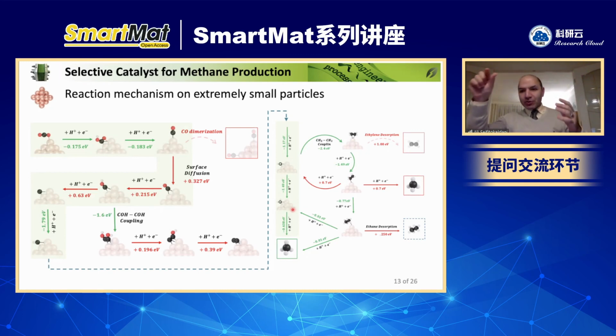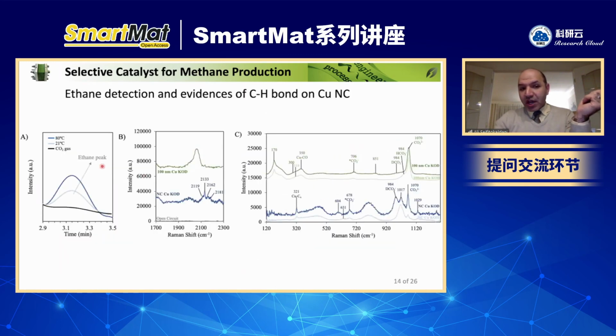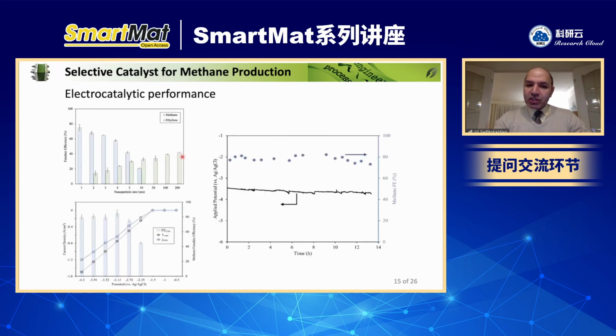So even if you produce ethylene using these small particles, even in alkaline electrolyte, which basically favors CC coupling, because it remains and doesn't leave the surface, it will eventually be converted back to methane. That's why we produce larger amounts of methane. This is, again, our hypothesis. We try to support it through different experiments, such as looking into the ethane desorption, or through Raman spectroscopy, looking at what happens to the CC coupling and the CH2 population on the surface, which supports it. Eventually you see the trend that the small particle doesn't really produce ethylene, most likely because it is converted to methane.